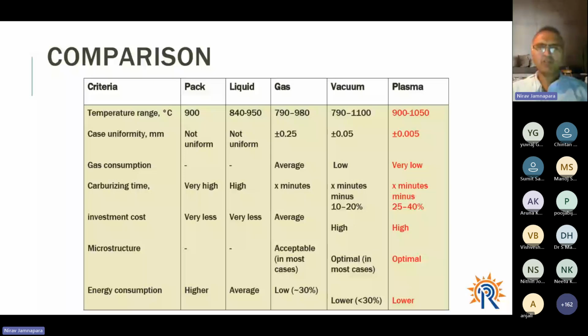The investment cost is very high because of high capital equipment. The microstructure is acceptable in most cases of gas carburizing, and it is optimal in most cases of vacuum carburizing. Plasma carburizing is, of course, the most preferred one, with an optimized microstructure. The energy spent is lower in vacuum carburizing and plasma carburizing as compared to all others.